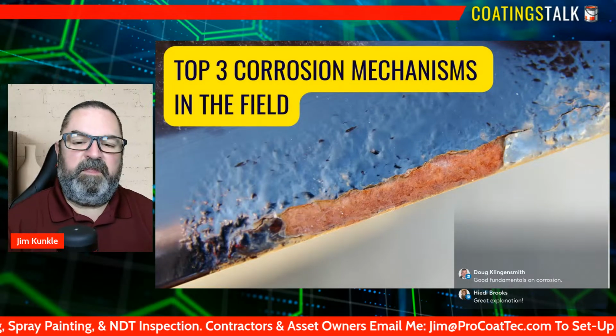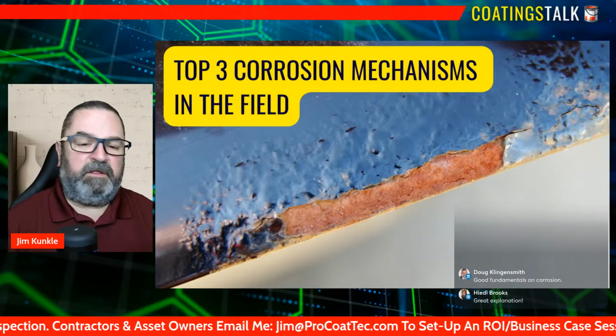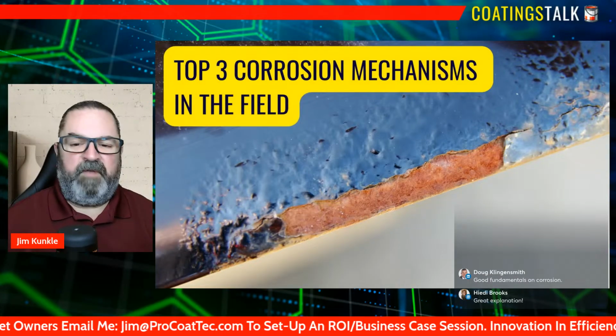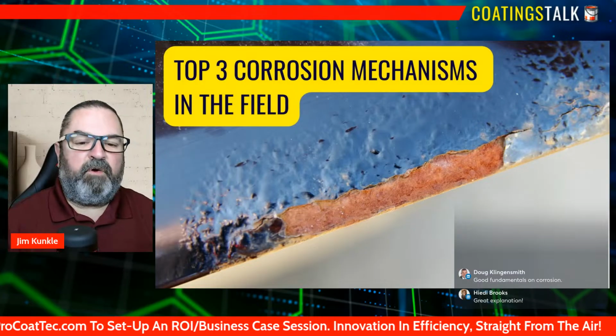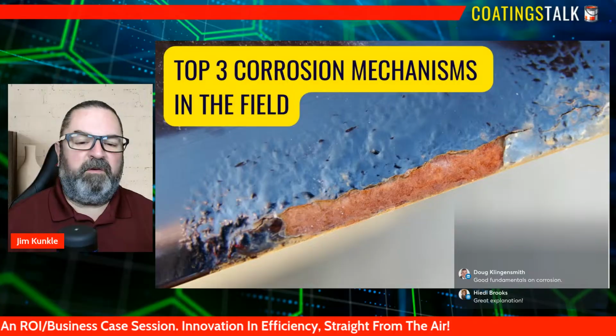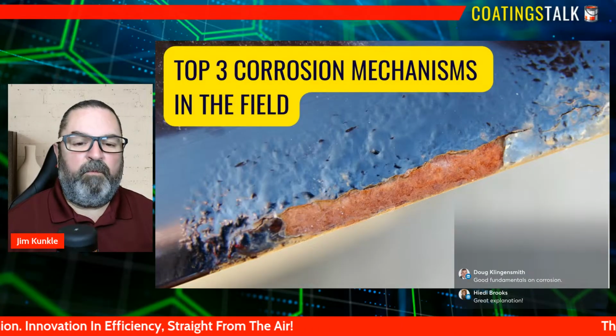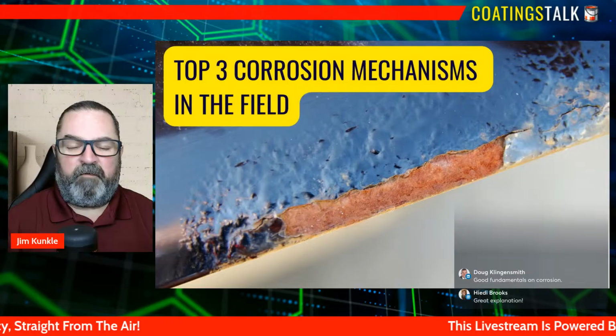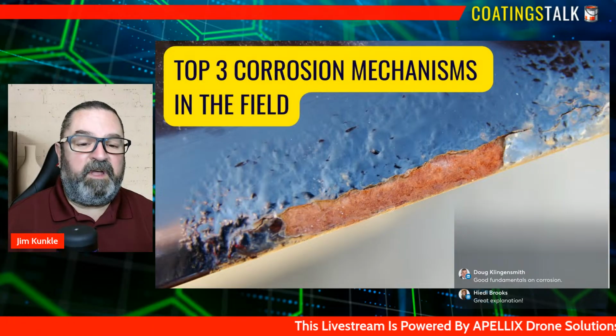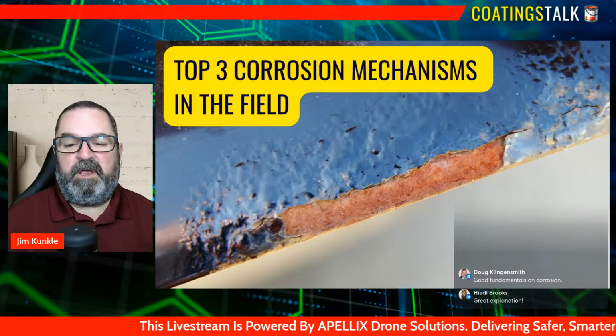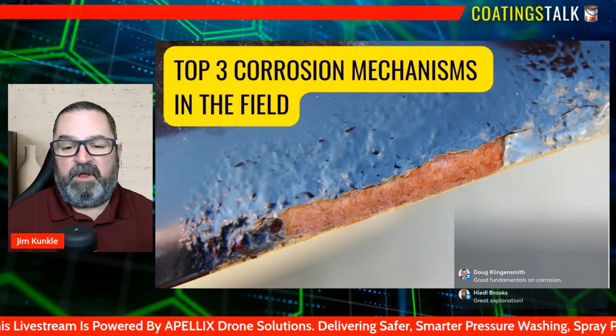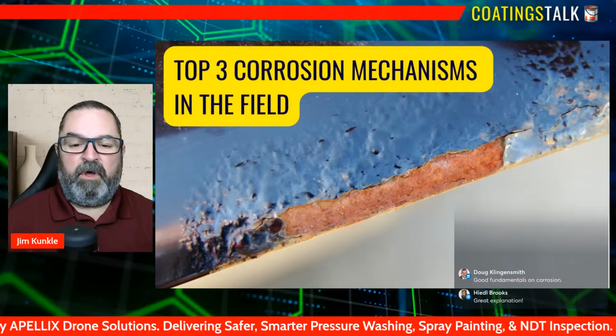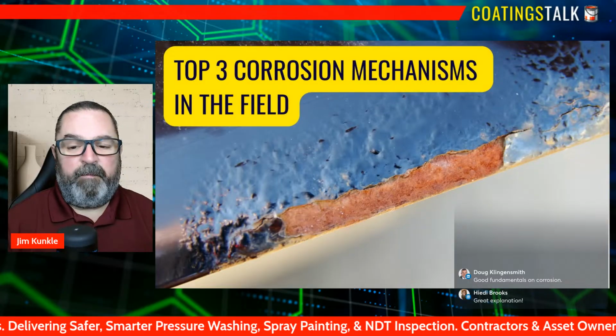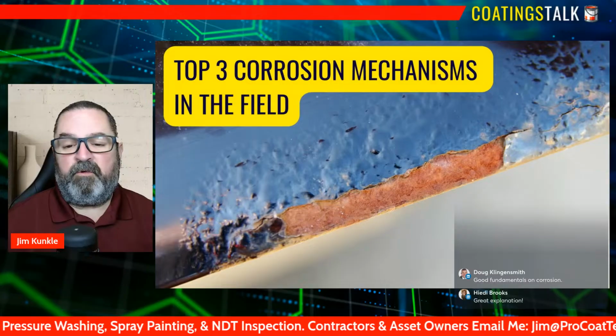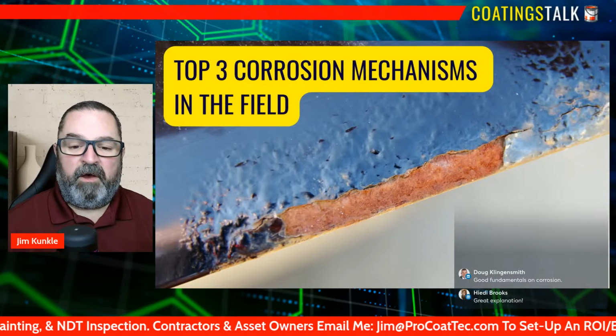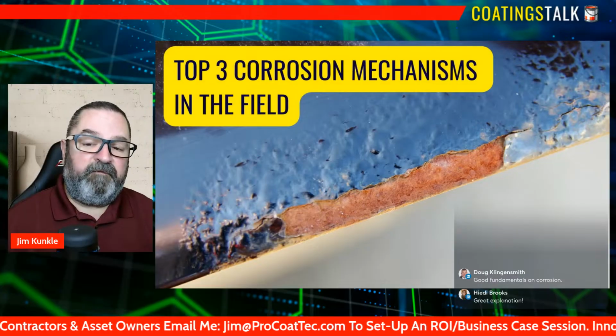This process is driven by the natural differences in electrical potential between the two metals. Field teams often see this with mixed metal fasteners, clamps, supports, or repairs that were a quick fix. Unintentionally, what they've done is create a corrosion cell that accelerates metal loss on the more active material. And what makes galvanic corrosion especially important for field professionals is how quickly it can progress once the cell is established. A carbon steel component connected to stainless steel, for example, can experience rapid localized attack that goes far beyond normal uniform corrosion rates. And the damage often appears as concentrated pitting or deep grooves near the connection point. Smaller areas that can lead to big failures if overlooked.